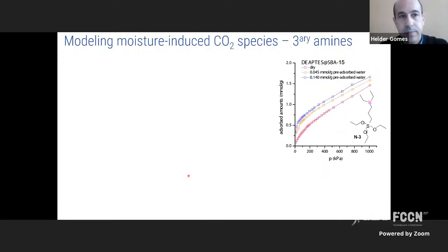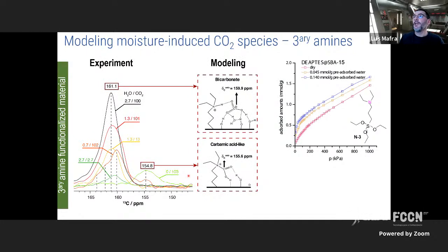We have tried also to do the same in tertiary amines, where we put moisture in tertiary amines, and we see now there is a difference. If you have the isotherms of dry samples and you expose previously to water before adsorbing with CO2, you see now an enhancement of CO2 capture. And you see the peak always increasing. That proves that you really have an increase of CO2 species that are formed in the pores.